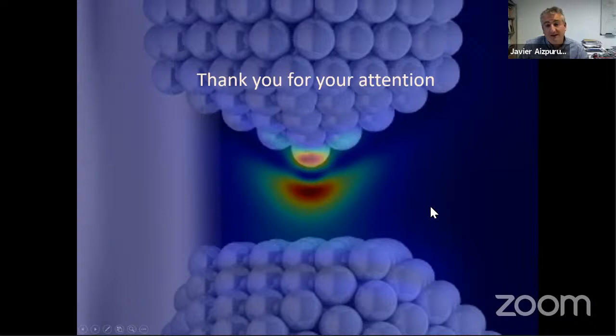a very important effect that I didn't mention, but is extremely important in emission from molecules to the far field, is that the exciton can be quenched. And if you put your molecule too close to the metal, once the exciton is formed, it immediately will decay into metal excitations, into heat and everything, right? So the decay of the exciton into the metal by direct touch is really harmful.